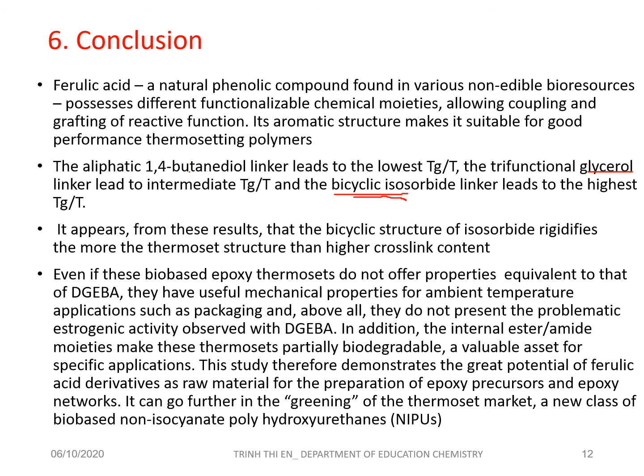above all, they do not present the problematic estrogenic activity observed with DGEBA, and in addition, the internal ester or amide moiety makes these thermosets partially biodegradable and a valuable asset for specific applications. This study therefore demonstrates the great potential of ferulic acid derivatives as raw materials for the preparation of epoxy precursors and epoxy networks. It can go further in the greening of the thermoset market, with a new class of biosourced isocyanate-free polyhydroxyurethane, and this is the meaning of the article and is very useful to create a new thermoset.